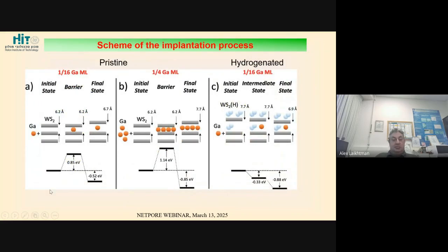And here you can see the diagrams for the case of pristine nanoparticles, not hydrogenated, and hydrogenated, and you can observe that we absolutely removed the implantation barrier. I'm not showing you here, but we also performed later the electrical conductivity measurements on these gallium implanted nanoparticles.